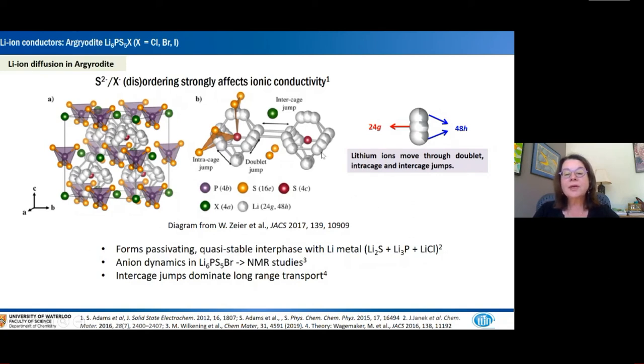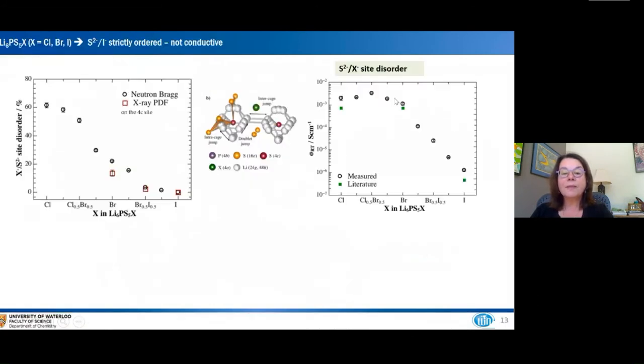The point here is that there are two different positions for the anion, which is either sulfide or the halide, for example chlorine or bromine. These are the 4C positions and the 4A position. For the chlorine and bromine Argyrodites, these are completely disordered - the sulfur and the halide are completely disordered over both of these sites. Whereas in the case of the iodine, it is completely ordered. And this results in very low conductivity.